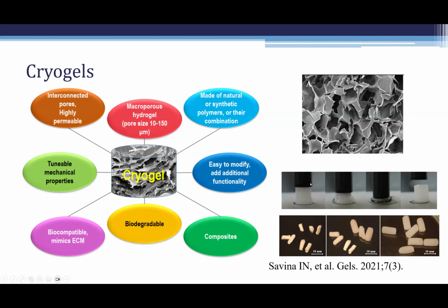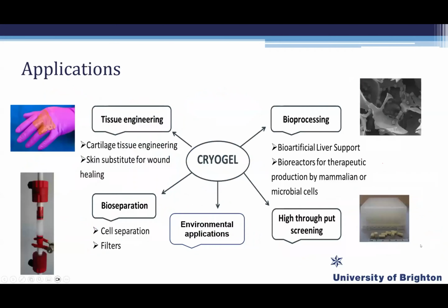You see it in the images as well. It shows the compression. If we compress the gel, you see that the water is simply squeezed out from the gel. When we release the load, the gel takes the same shape as it had in the beginning. We have repeated this a few times and see that not much damage has been done, depending on what conditions you made the gels in and what polymer you use. It's also easy to reswell from dry polymer. All of this then leads to different applications.